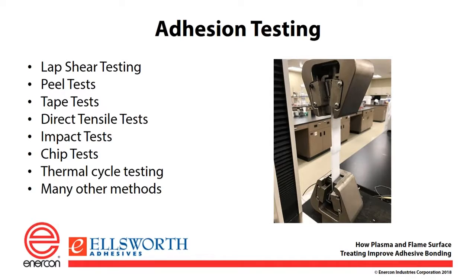Thermal cycle testing involves going from cold to warm temperatures and then warm back down to cold temperatures, which frequently causes deformation in the parts. You get shrinking, contraction and expansion, and differences in these can cause adhesion failure that you do not see under ambient conditions. There are many, many other methods. This is just a short list of different test methods.